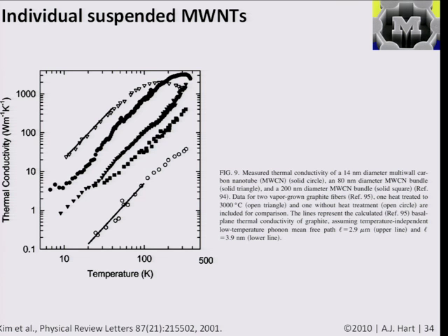And then you notice they all drop down pretty sharply with temperature. And that's from that effect of specific heat. So the number of available modes, as you go lower, it becomes lower, and there's just less vibration to carry the heat. And then at very high temperature, it also starts to curl down again. And that's because now we're getting into the regime where there's more scattering, and that will limit heat. So this will also have a peak, and some of these others would if we carried them out a bit farther.